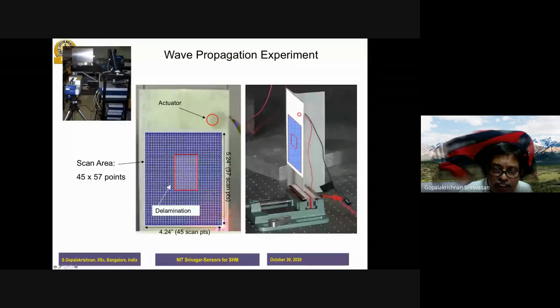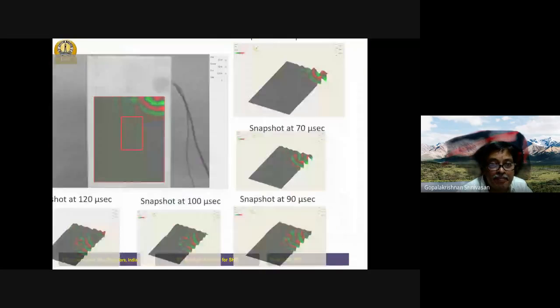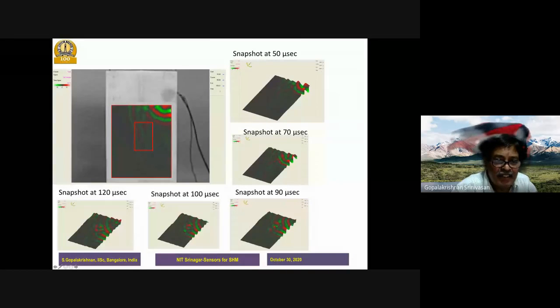So here is a T-pull joint, a co-cured, co-bonded joint, where you have the skin and the stiffener. I trigger this piezo actuator on the skin. The measurement I do is on the skin, and based on the measurement I infer what is happening on the stiffener. That is the area that I'm measuring. For example, in an area of 4.2 inches, I have 45 pixel points. So I can get that in a small area. Imagine I can even pixelize much, much finer, depending upon my grid size. So this is a trigger.